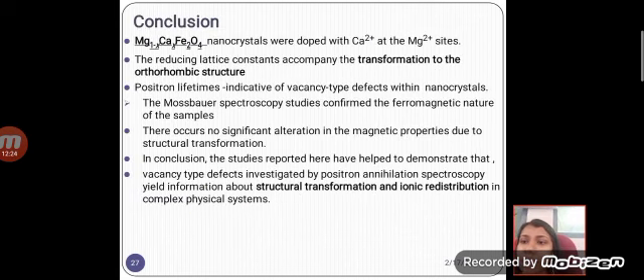Now moving to the conclusion. We have synthesized magnesium calcium ferrite nanocrystals doped with calcium at Mg2+ sites. The reducing lattice constants accompany the transformation to the orthorhombic structure. And our final conclusion is that the vacancy type defects, as investigated by positron annihilation spectroscopy, yield information about the structural transformation and the ionic distribution that occurs in ferrite nanosystems.